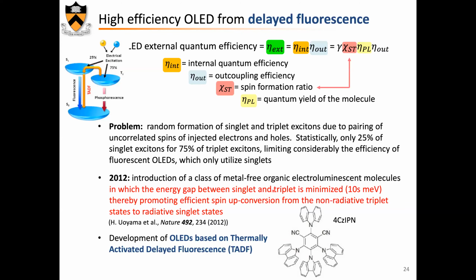And that, of course, leads to, given that these triplets are non-radiative and they stick around for quite a while, that allows to promote an efficient reconversion, or spin-up conversion, from the non-radiative triplet to the radiative singlet. And therefore, again, you recover most of the triplet and you get a very efficient OLED. So this is what is called thermally activated delayed fluorescence, as it goes back to fluorescence after that. So this is another very important aspect of OLED these days.